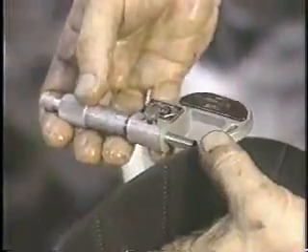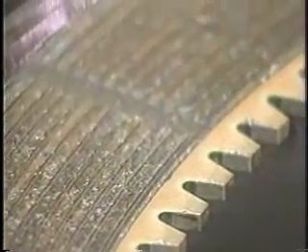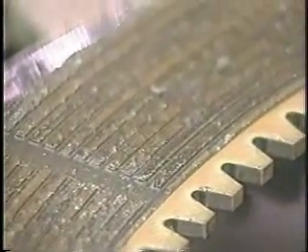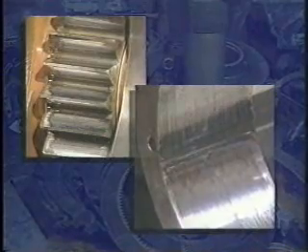Slippage increases friction and heat. Heat causes the plates to warp so that they wear unevenly. They contact each other only at high points and wear away friction material. Bits of this friction material move through the system like little cutting tools. Damage can be significant, as you can see in these prematurely worn parts.